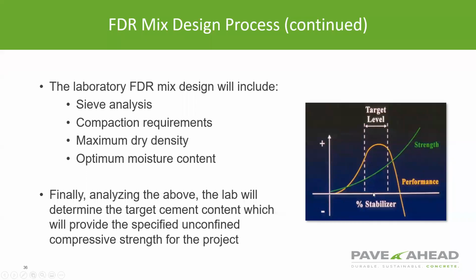If we're above this percentage of cement target area, you can see our performance drops off. If we're below the optimal cement content target, what we find is we don't have enough strength in that base below the pavement, particularly a flexible pavement, in order to provide for the load carrying capacity. So we want a good stiff subgrade.